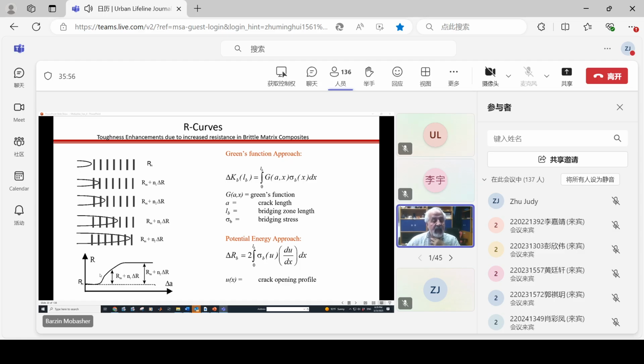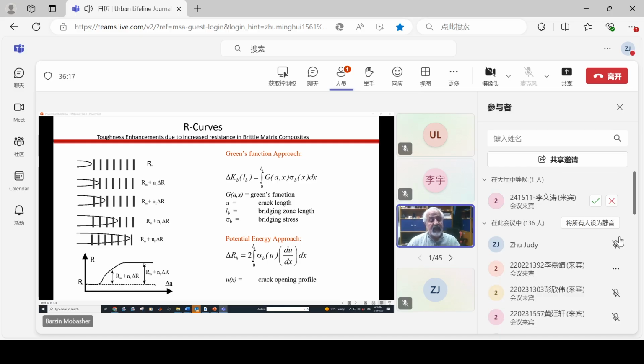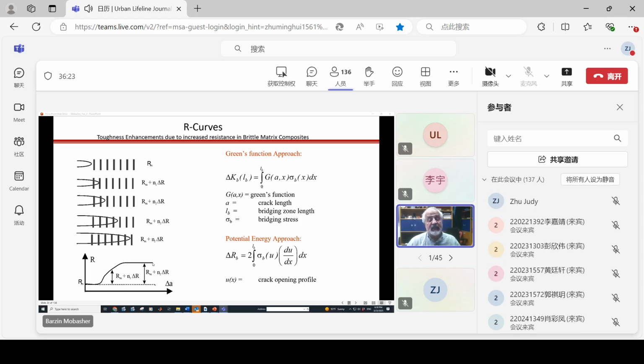So technically, I start with a resistance that's very low. As the crack is growing, this resistance is increasing in a nonlinear way, and I reach a point of steady state cracking. Now, steady state cracking is what basically everybody's used to. This is the fracture mechanics part. But look at what I have done. I have increased the amount of energy. By allowing a certain amount of stable crack growth, I've allowed more energy for the steady state.